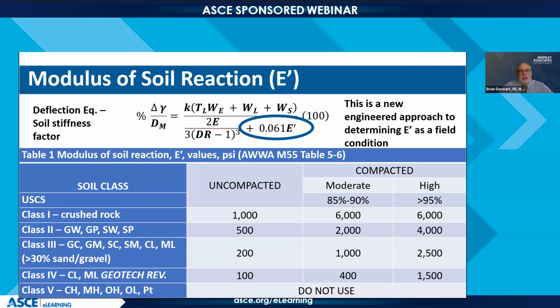Recognize, however, also in the long term, this same equation gets used for pipeline rehabilitation quite a few times. It's one of the main formulas, or the base form is for F1216 for rehabilitation or putting in CIPP liners. The issue there being you have now a trench that is stabilized. You're trying to put in a CIPP liner. If the pipe is in the trench and it's happy, in other words, it hasn't failed or anything like that, you really don't have any load. All the load on your CIPP is going to be carried by the host pipe. So the E prime is dependent on what the host pipe is seeing, so not necessarily on your rehab pipe. So just a caution I've seen over the years, but soil-structure interaction, very important.